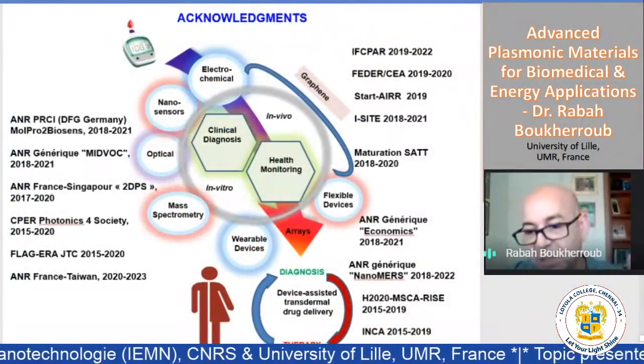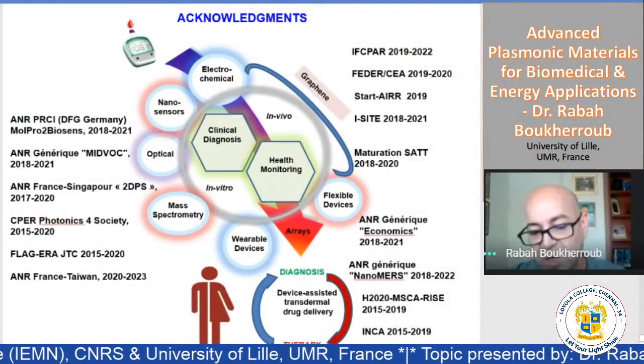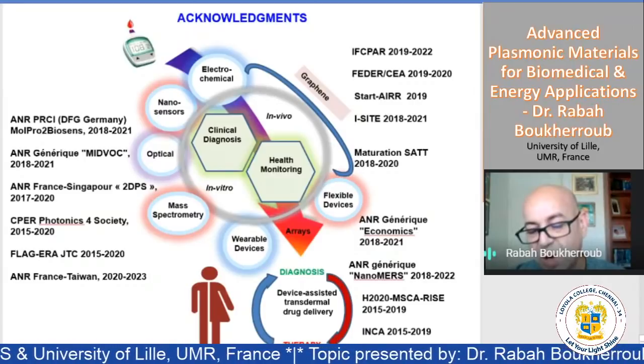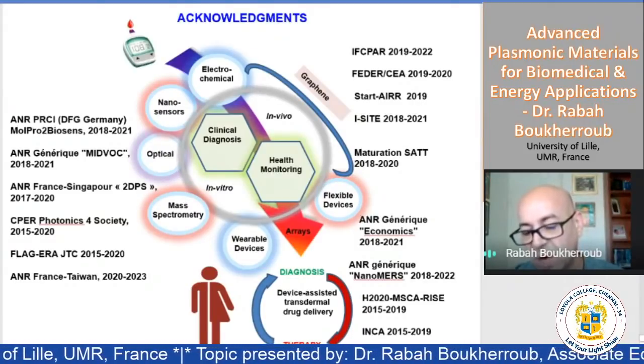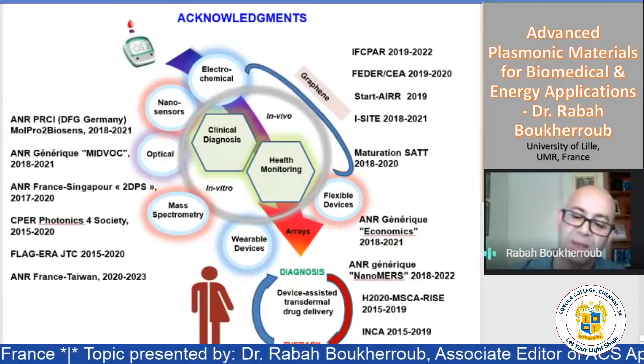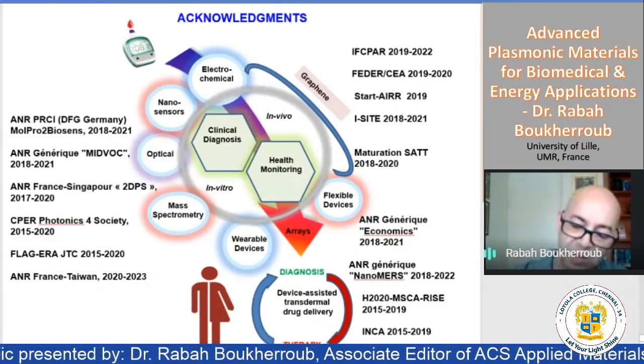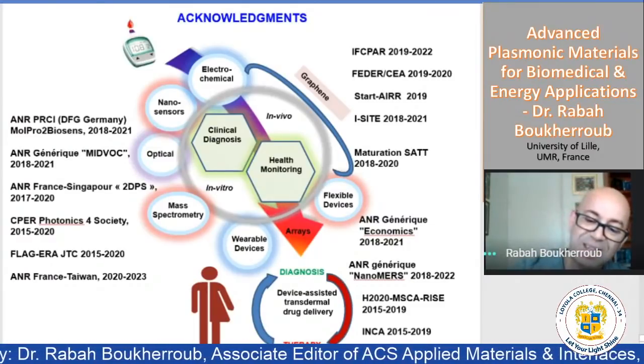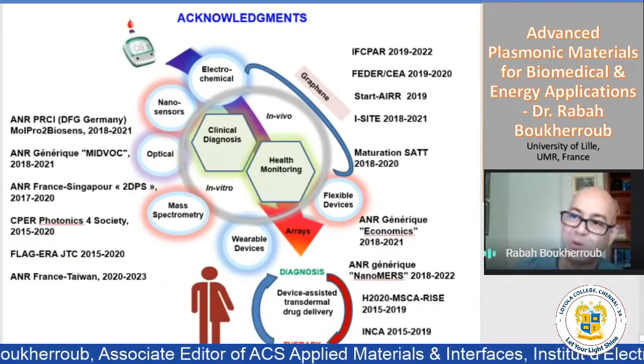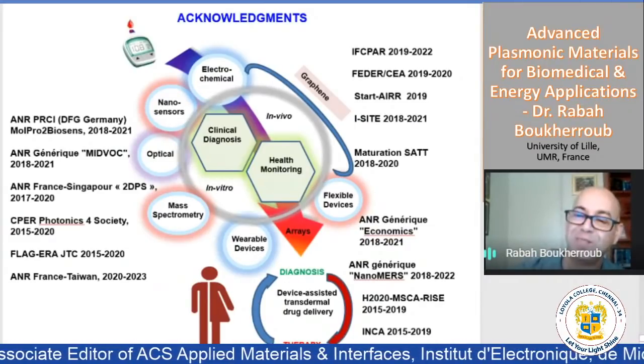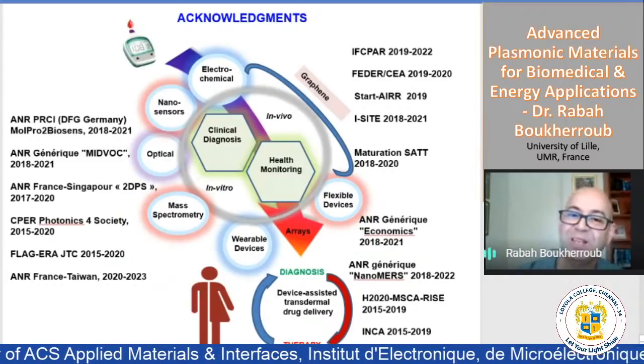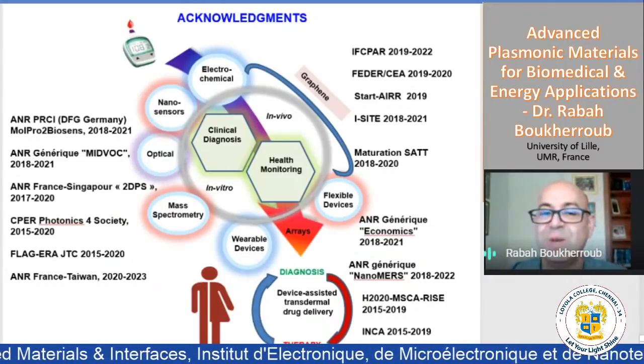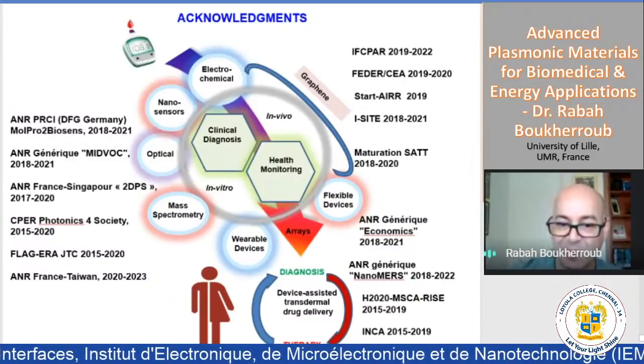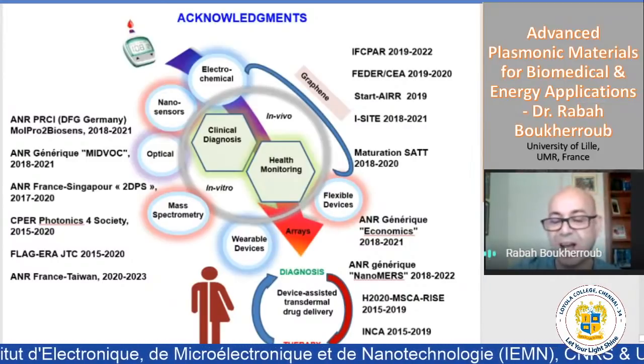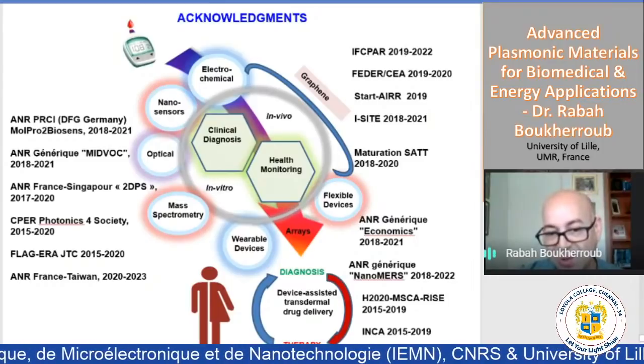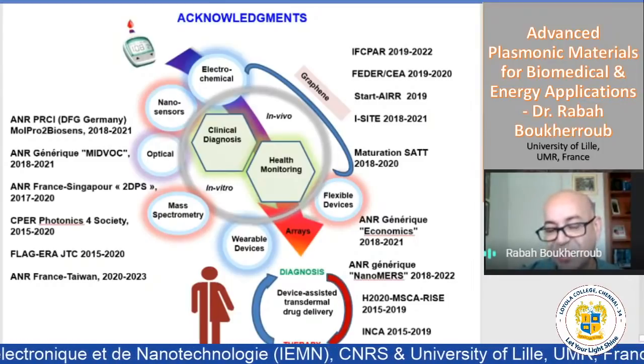However, on graphene, the concept is completely different. The single DNA strand is just absorbed on graphene through pi-pi stacking interaction. And when you do the hybridization with the complementary DNA, this is actually released from the surface. So in a way, you measure a negative signal, you lose signal, while in a normal SPR you measure a signal that is added on the surface. With graphene, you measure a signal which you lose because you lose the material, so in a way it's a negative signal.